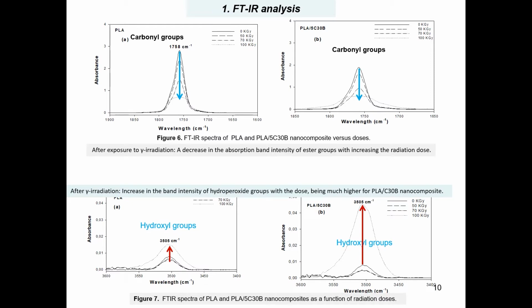After gamma irradiation, we notice a decrease in the absorption band intensity of the ester groups in both samples with increasing radiation dose. Whereas for the hydroxyl groups, after gamma irradiation, we observe an increase in the band intensity of these groups with increasing radiation dose, however much higher for the PLA Cloisite 30B nanocomposite. This indicates the occurrence of some chemical reactions and some oxidation reactions.